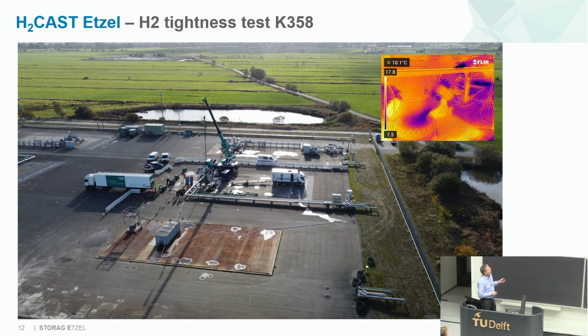And what we have seen here was something for emergencies. If we need a high pressure drop, a release of hydrogen, we can pump it or bring it into a water-filled tank and a flare which we have built for this, just in any case to get a quick release of hydrogen. Maybe in the break I have also a film, because at the end of the test we had to flare the hydrogen. I have a film which takes about 1.5 minutes. It can show how we ignite the hydrogen, how it burns.